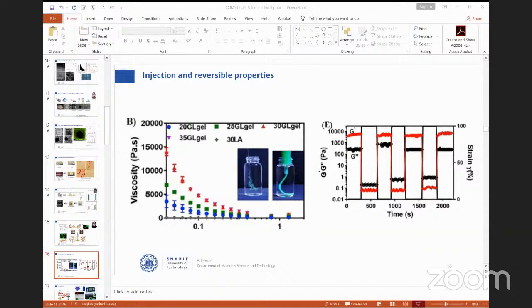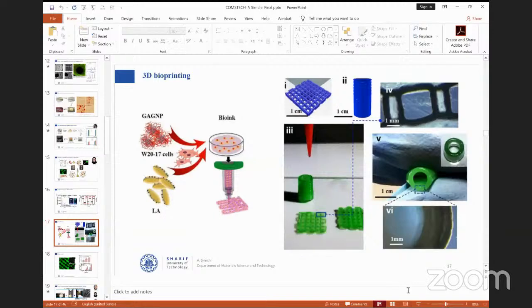So we prepare the material, we print it very easily by inserting force. And as soon as it is printed, it becomes a gel and makes it stiff. The most important thing is that these materials are printable, and also we are able to load cells inside the printing. As you see here on the left-hand side, the GAGNP nanoparticles are combined with laponite, and we also loaded W20-17 cells inside and then printed as a scaffold, as you see in this figure.